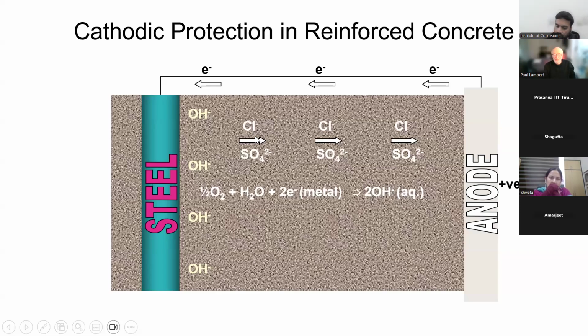There are systems that are used specifically to increase alkalinity, sometimes called electrochemical realkalization, but you get it with cathodic protection anyhow. You can also optimize the chloride removal by electrochemical chloride extraction, but you get it with cathodic protection anyhow. The other thing that happens is in an electrical field, water moves and it moves away from the steel. You can get systems that just do that, electroosmosis, but you get it in cathodic protection.